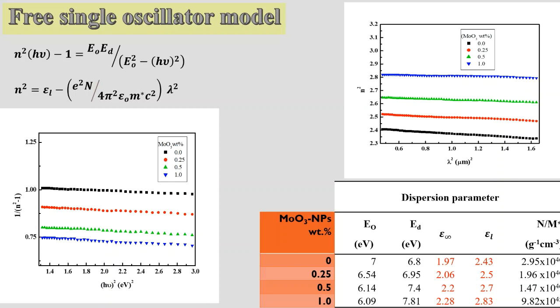From the relation between h mu square and 1 over n square minus 1, we can calculate the oscillation energy and dispersion energy, which we can see here. From the relation of n square as a function of lambda square, we can calculate lattice dielectric constant and the free carrier concentration. We observed that there is a difference between lattice dielectric constant and high dielectric constant, which indicates that there is free carrier concentration.